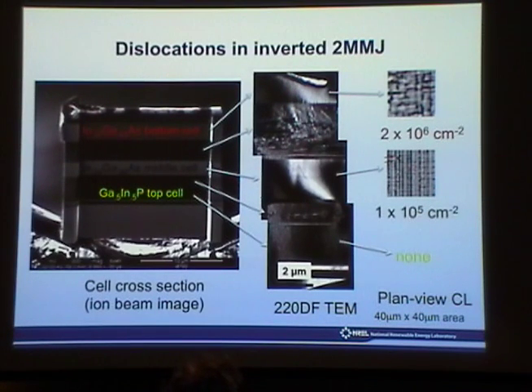And if you look at cathodoluminescence, which essentially maps out dislocations, there's essentially none in the field of view on the high-quality top cell. There's about 10^5, which is a very low number, in the middle cell, and about 10^6 in the bottom cell. This is sort of what we aim for in terms of dislocation density. Much more than that, you start to decrease your VOC, your open circuit voltage.